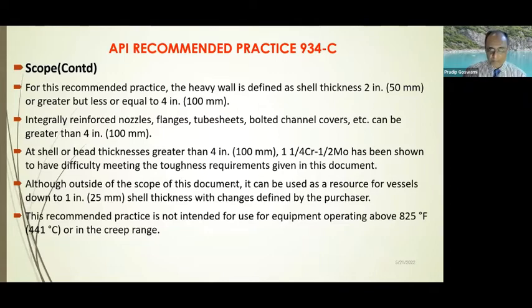And this recommended practice, this RP, is not intended for use for equipment which is above 441 degrees centigrade or 825 degrees Fahrenheit, or in the creep range. There is another RP which I'll talk about later that is generally followed for fabrication of such equipment which would be operating at above 440 degrees centigrade.